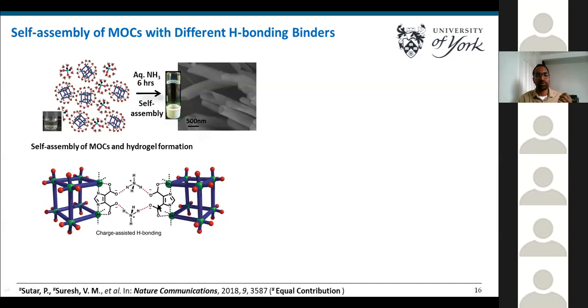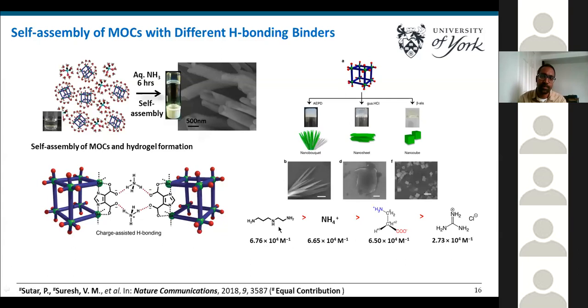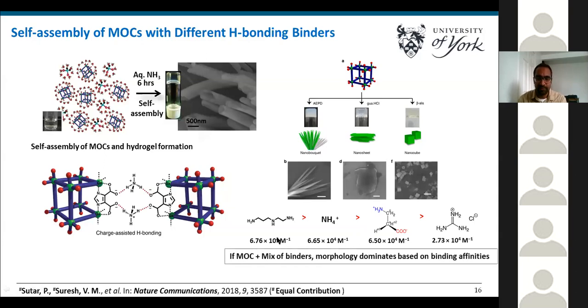So we want to generalize this concept that metal organic cages can self-assemble to form hydrogel in the presence of hydrogen bonding molecular binders. For this, we chose different molecular binders: aminoethyl propanediamine, beta-alanine, and guanidine hydrochloride. In all these cases, when we add the molecular binders to a MOC solution, we see immediate gel formation, as you see here. And scanning electron microscopy images show that each gel has different nanostructures. We have also tested their binding affinities, and we found that aminoethyl propanediamine has the highest binding affinity compared to all other molecular binders, and guanidine hydrochloride has the lowest binding affinity.